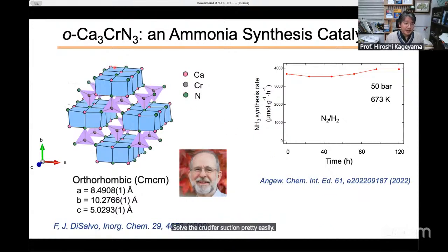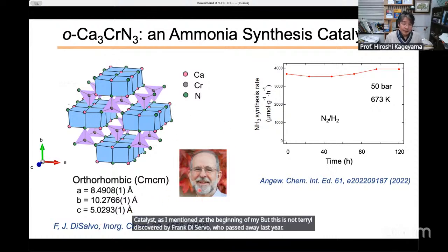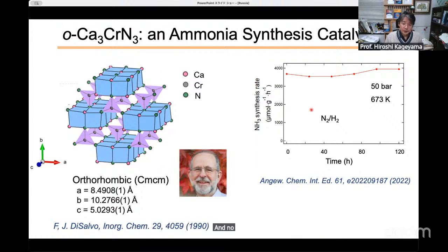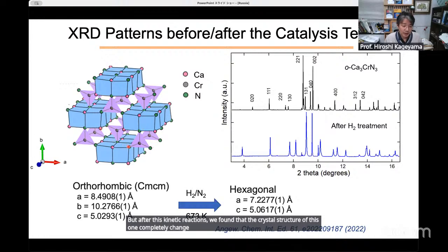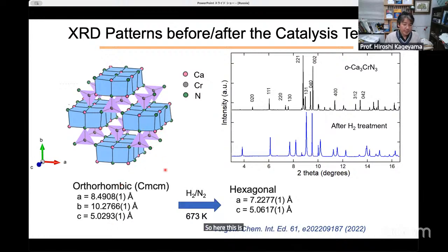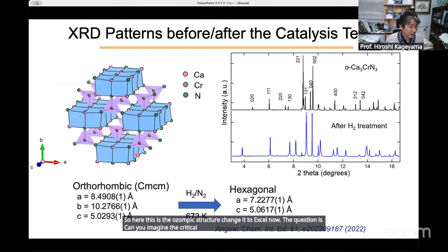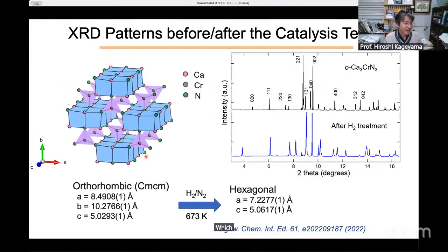But in this material, my former student worked on this material for ammonia catalysts, as I mentioned in the beginning of my talk. This material was discovered by Frank DiSalvo, who passed away last year. This material shows very high ammonia synthesis catalytic activity. But after these catalytic reactions, we found that the crystal structure completely changed into a hexagonal one. Here, the orthorhombic structure changed into a hexagonal one. The question is, can you imagine the crystal structure of the final material? We couldn't. That is very difficult.